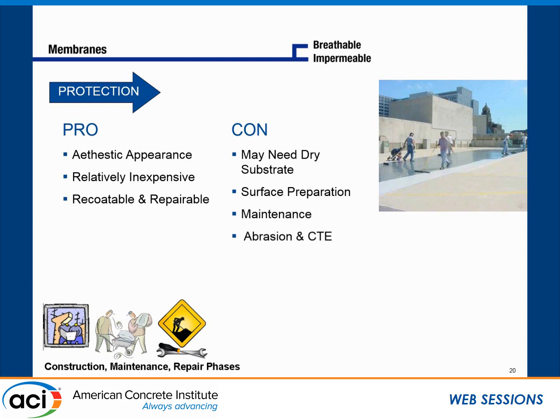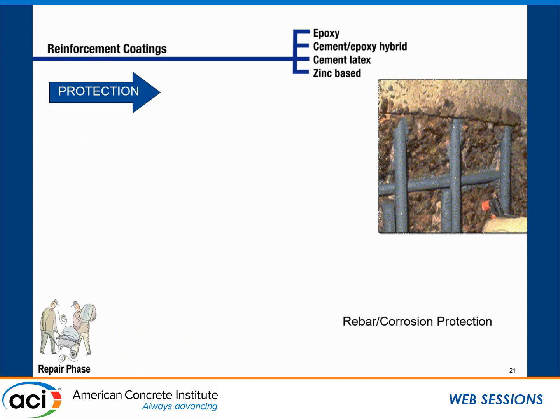Abrasion and coefficient of thermal expansion differences may affect them, but snow plows are the biggest damager. A snow plow scrapes off the membrane, you now have holes, and de-icing salts get in. They may also trap moisture because they're impermeable. Fill the concrete up with water and let it freeze, bad things happen. I've got total saturation, and my air void structure may wind up not being effective.